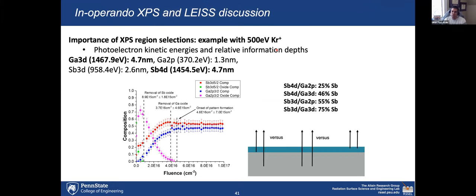But what was really interesting was what was going on in the subsurface. As I opened this talk, I had mentioned that it's not only relevant for us to use one technique in situ to measure the surface composition, because you might think, well, you use ion scattering to just measure composition, right? You measure how much antimony is there to how much gallium is there, but that's really not what's relevant. What I want to emphasize is the relevance is with the dynamics of these components as they are moved or they change through from the radiation from surface layers to the surface layer.